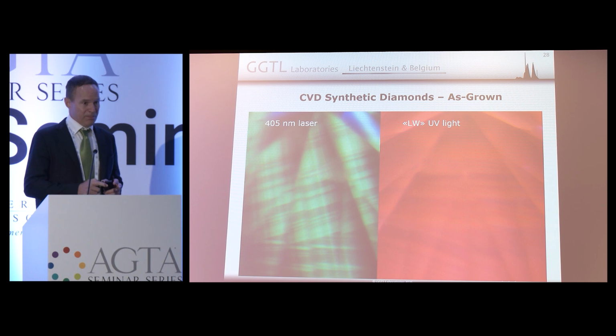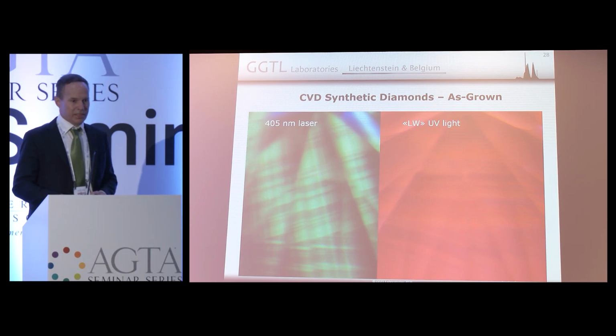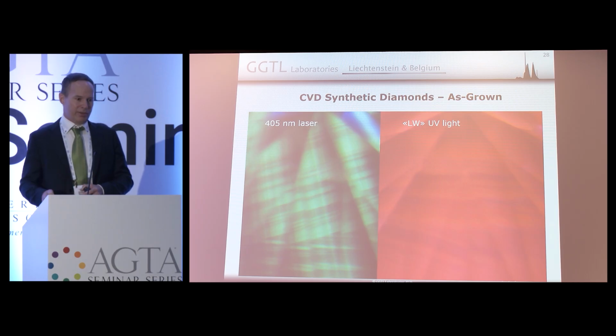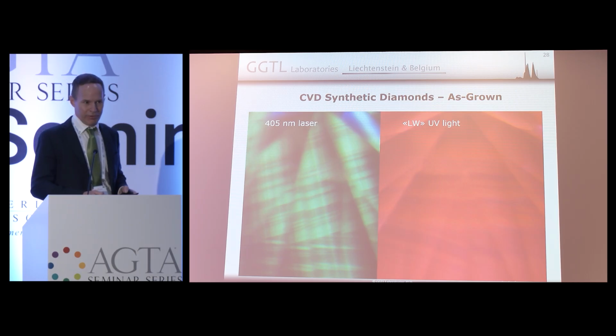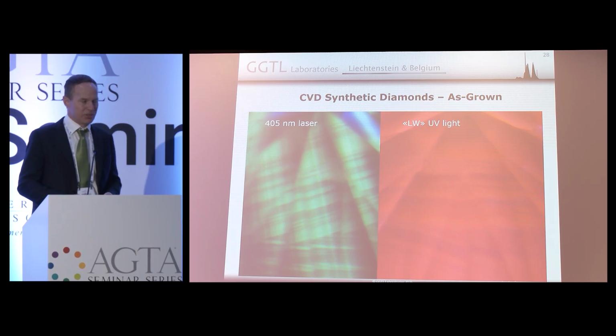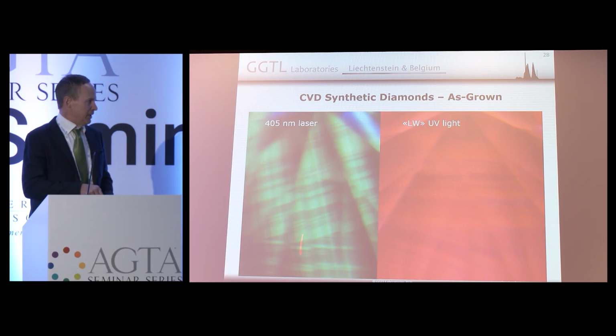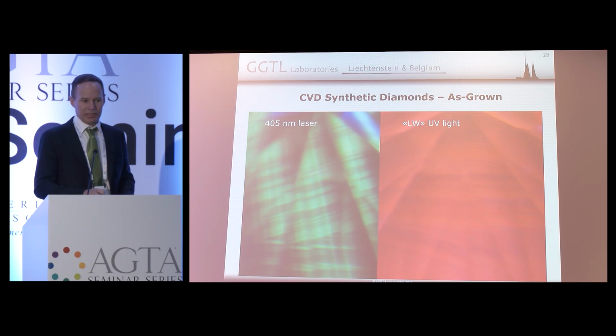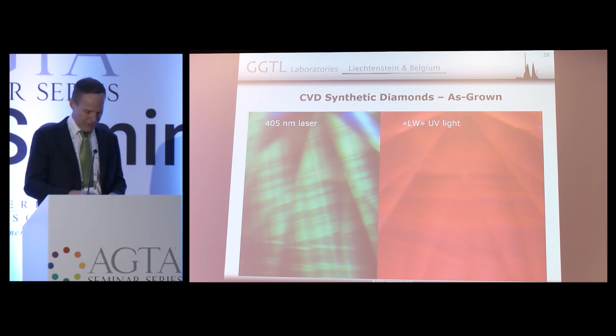So these stones typically show two defects when they're as grown. That's quite distinct. One is the NV center. The NV center emits in the orange, so that's it. The NV center is well excited with long wave UV, but not very well with 405 laser. So depending on what you use, your stone's going to be either orange or green. At 405, you're exciting the 467 nanometer defect, which is very characteristic for as-grown CVD diamonds.